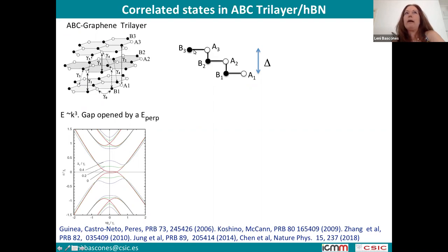So these are the two sublattices in graphene. In this system, even without the moiré, the bands close to charge neutrality are already quite flat. And if an electric field is applied, a gap is opened. You can see here, the different colors are for different values of the perpendicular electric field. So the electric field helps to tune the bands already in the system without the moiré.